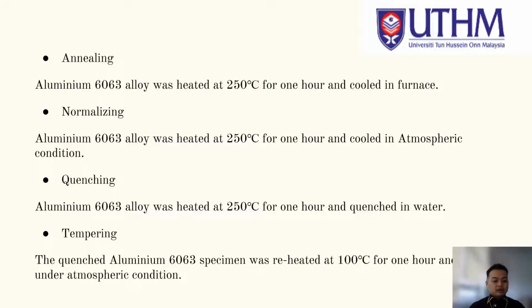Last, tempering. Tempering is the process of reheating the quenched specimen at low temperature over a period of time and cooling under atmospheric condition. In this research paper, the quenched aluminium 6063 specimen was reheated at 100 degrees Celsius for 1 hour and cooled under atmospheric condition. After completing the heat treatment process, the specimens were tested to find out the tensile strength and hardness. Tensile strength was tested in a Shimadzu AG-Xplus universal testing machine with crosshead speed of 20 mm per minute. Hardness of the heat-treated aluminium 6063 alloy was tested using a Rockwell hardness testing machine.